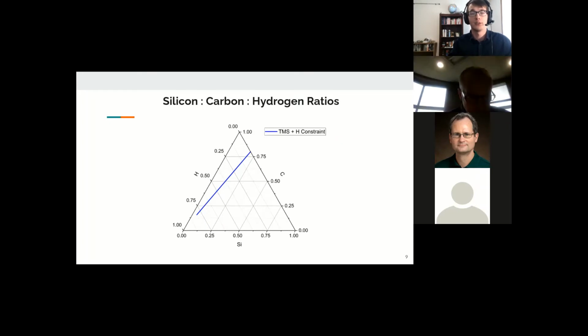silicon ratio. This figure is a ternary plot of the possible combinations of composition ratios between silicon, carbon, and hydrogen in the plasma. The blue line marks the only parameters that can be reached using TMS and hydrogen in our plasma. So that's why it's called the TMS and hydrogen constraint. And if you read the chart, you'll find that the blue line represents a constant 4:1 ratio of carbon to silicon, and it varies the amount of hydrogen. That 4:1 carbon to silicon ratio is again due to the precursor TMS. And this ternary plot represents the ratio of total atoms in the plasma. So it's just kind of a parameter space that you can get your mind around.